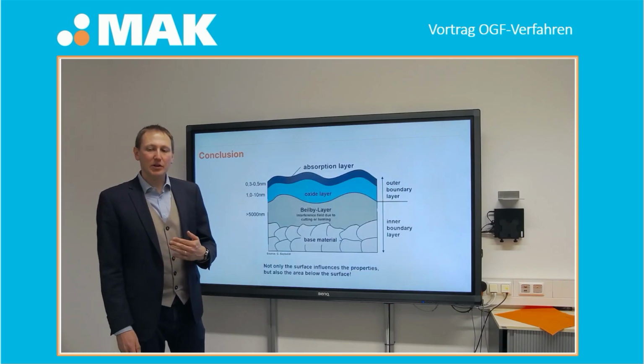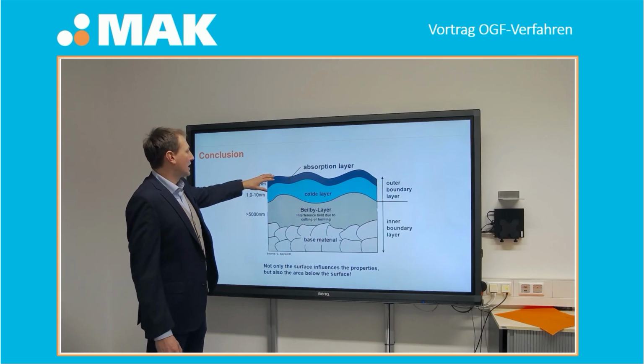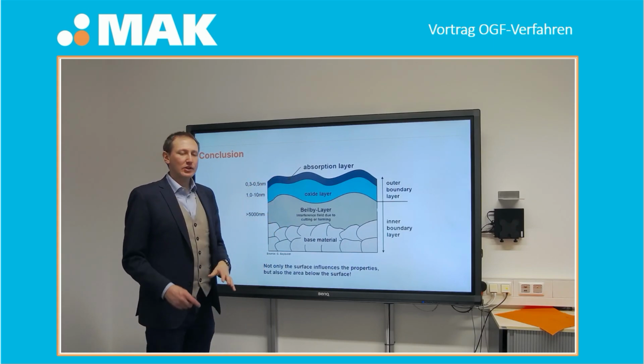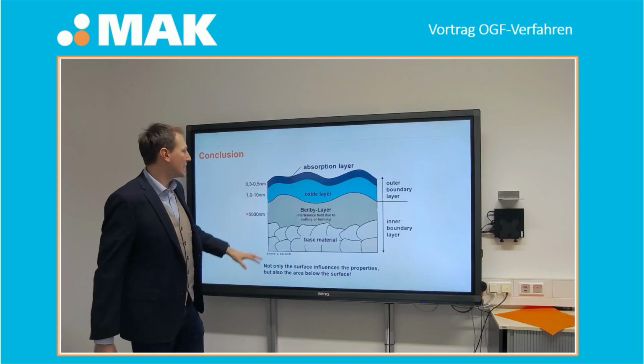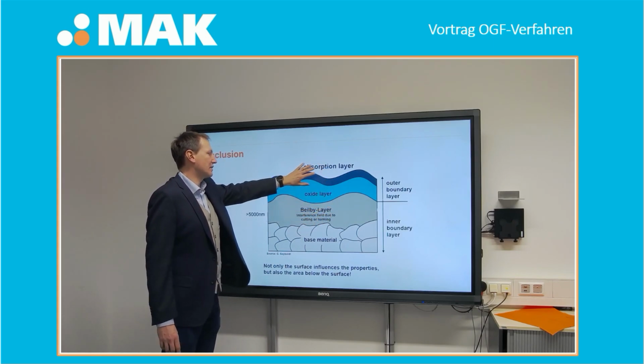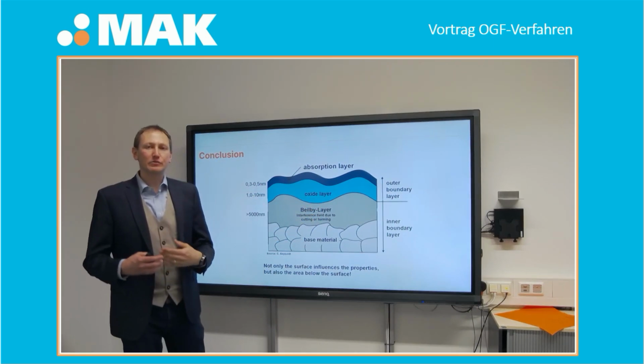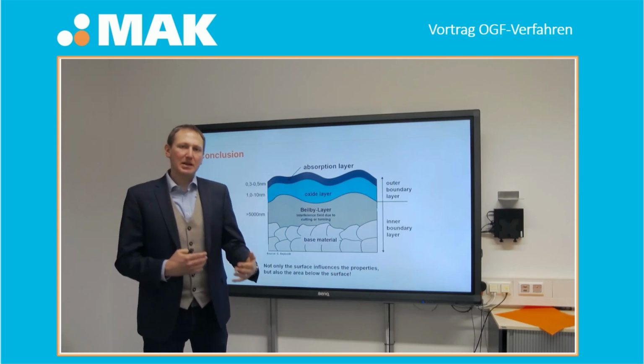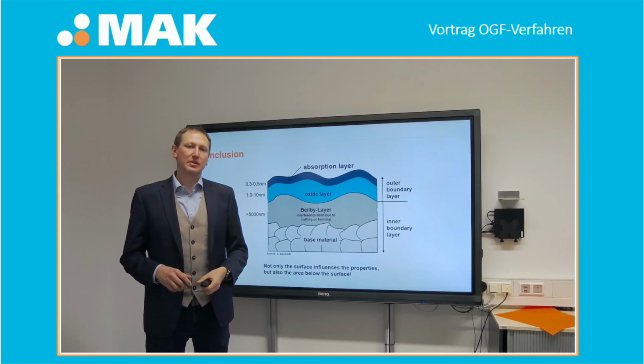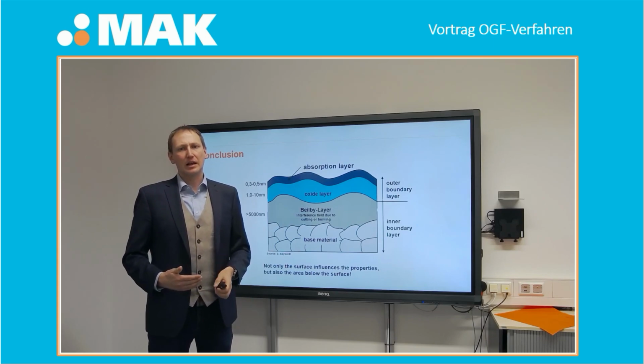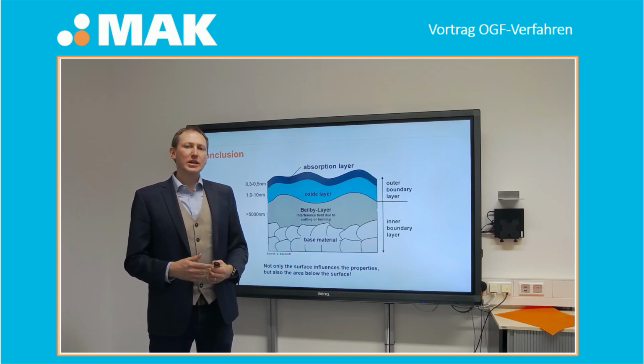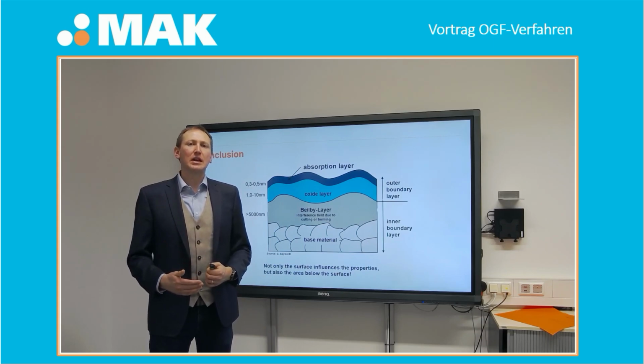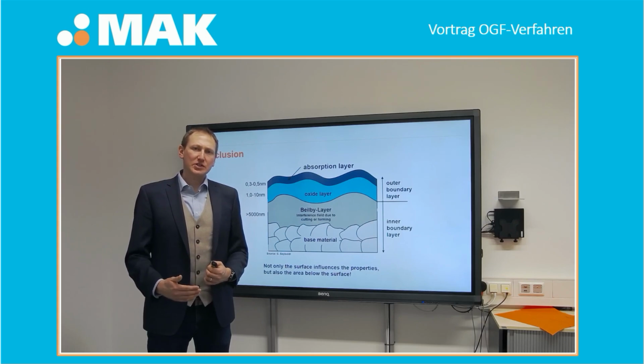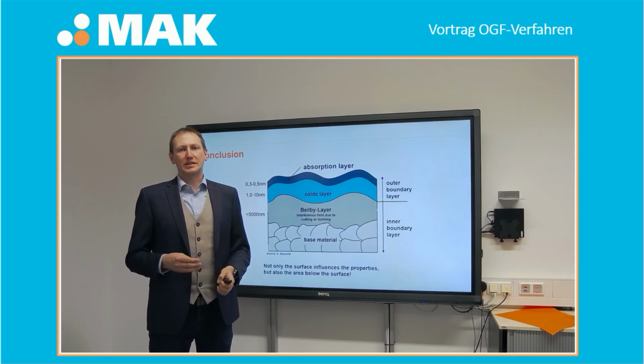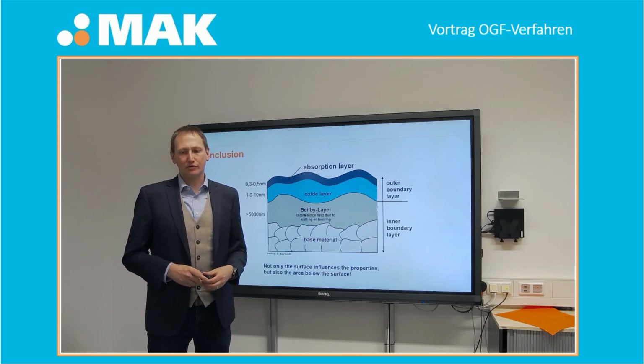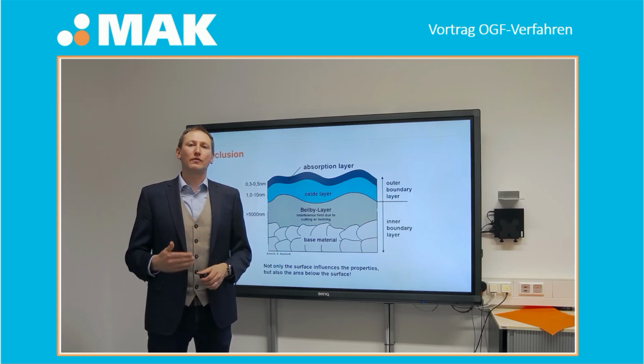So it's very important that you take into account that you have this Beilby layer, and every kind of machining process you do is influencing this surface and the Beilby layer itself. If you reduce the depth, this Beilby layer is less influenced by your machining. So if you do not do a very harsh machining, but a very slight machining, and reach a good surface condition by the slight machining, you have better surface conditions, you reach a better cleanability, and especially post-treatments like electropolishing lead to a better quality of your surface.